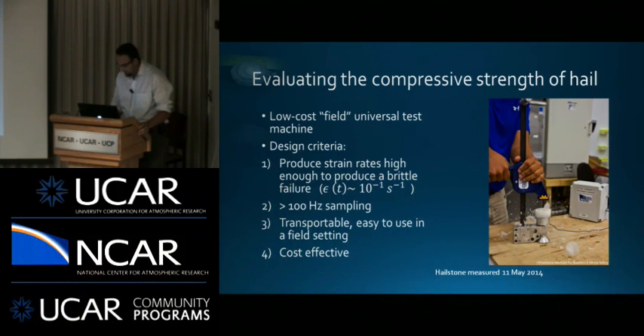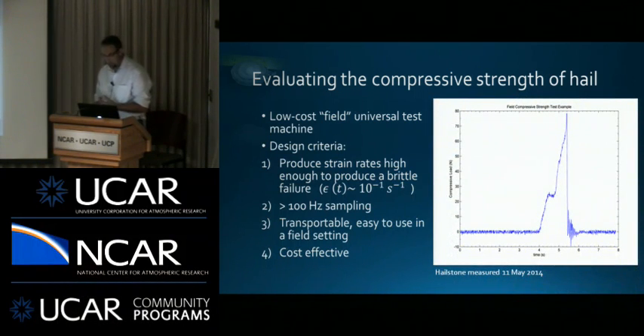The device we ended up with, and that's what some of the data looks like, is a simple handle device where you manually apply the load. There's a load cell in the bottom apparatus that measures the amount of force being placed on that stone. And so you get a record that looks like this, where you have a very sharp peak and then the drop off. That peak is what we're interested in. That's the peak at which it no longer could support the load and actually fractures. This is an example from a couple weeks ago of a stone we measured in the field.